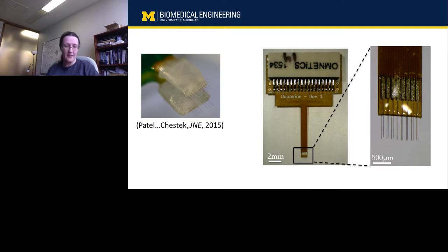And I should also say that longer than 500 microns, carbon fibers do penetrate, but it's not 100%. And if you want to put an array of closely spaced electrodes, you need it to be absolutely 100% of the electrodes that penetrate, because if one of them goes sideways, it can take out the rest of your array.